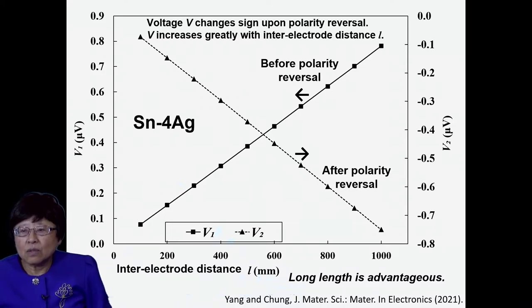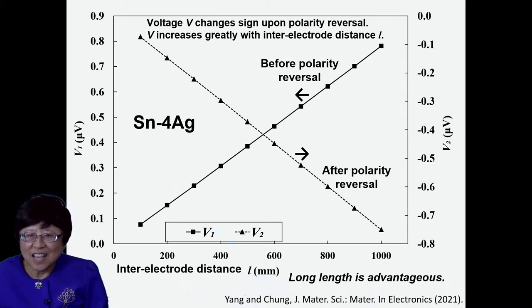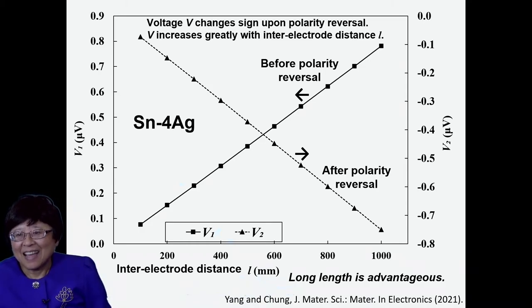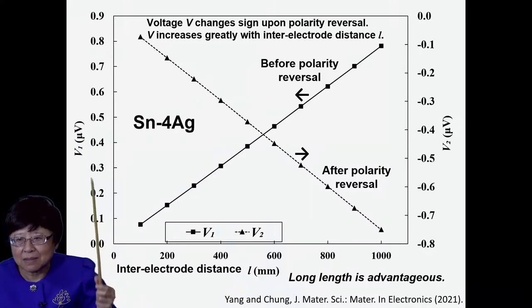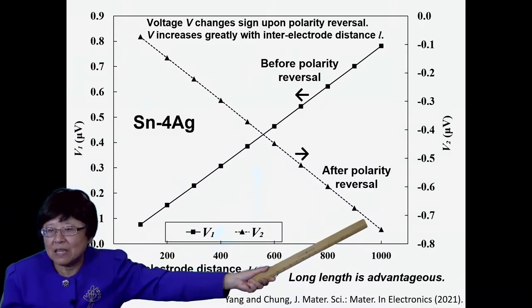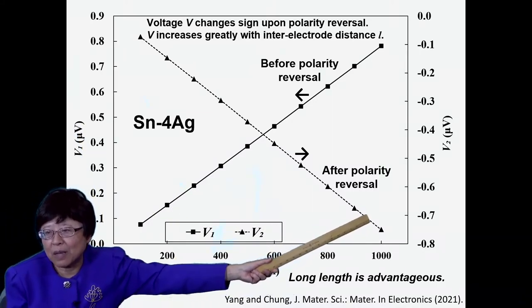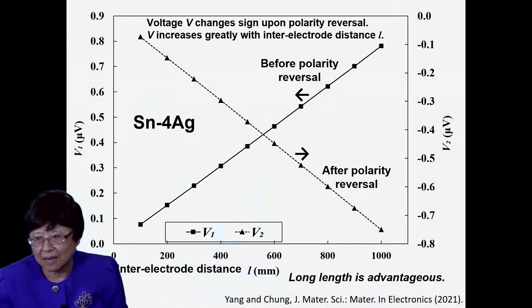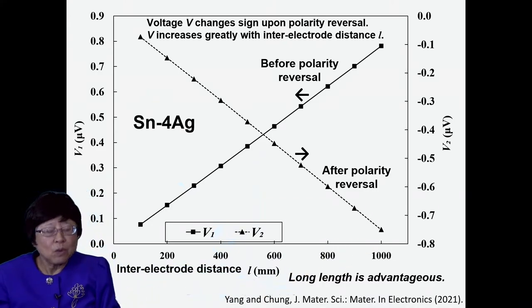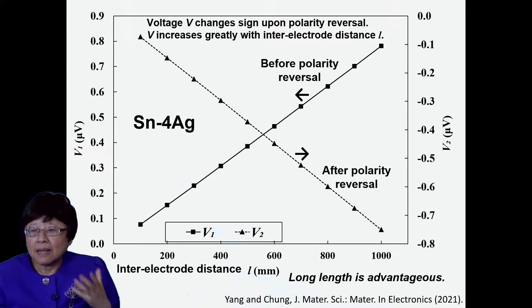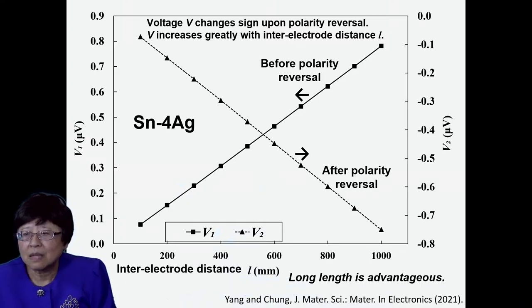Now, when you reverse the polarity at the voltmeter, the voltage obviously changes sign. It has to. And here, V1, before the polarity reversal, is positive, and this is V2. That's after polarity reversal, the voltage is negative. So that inherent voltage that I mentioned changes sign upon polarity reversal.